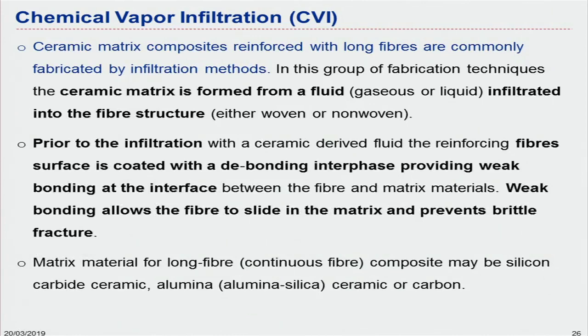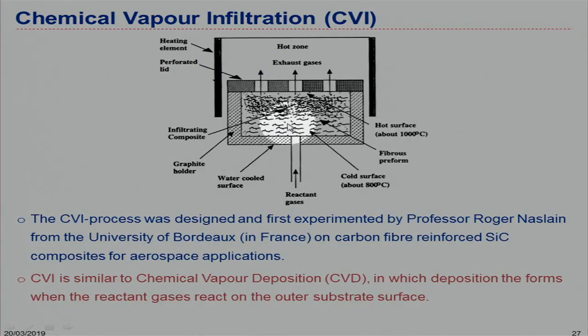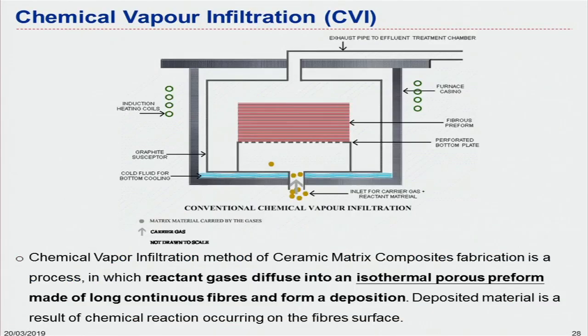With the fibers placed — let's say carbon fibers — before introducing the matrix material, we apply the interface coating material for the interface. Then we introduce the matrix material. The matrix could be silicon carbide, alumina, or carbon-carbon. It could even involve short fibers, but it is mostly suitable for long fibers. High temperatures are involved — sometimes up to 1000°C or more.